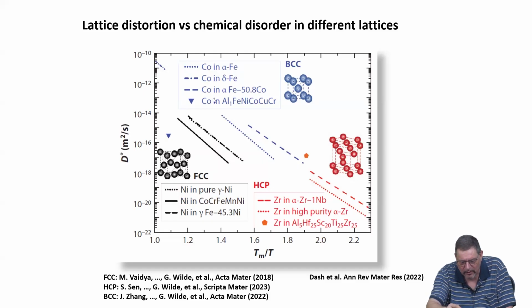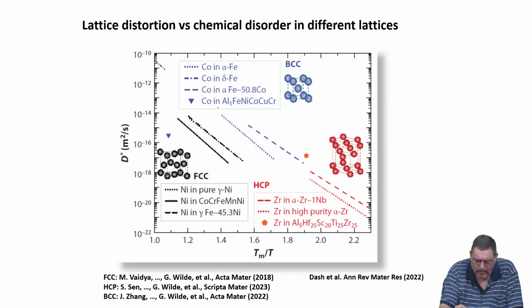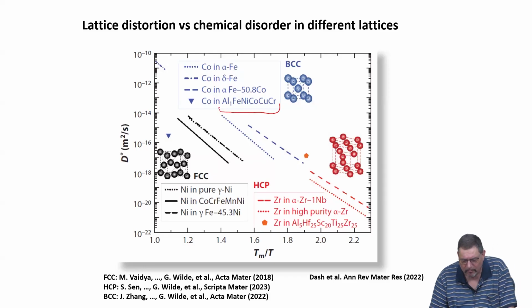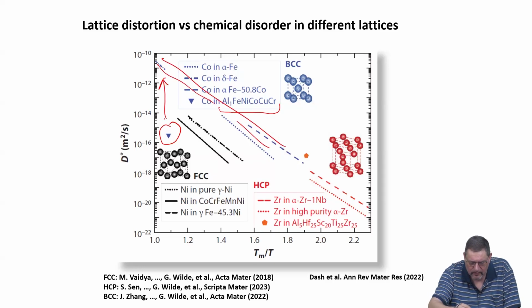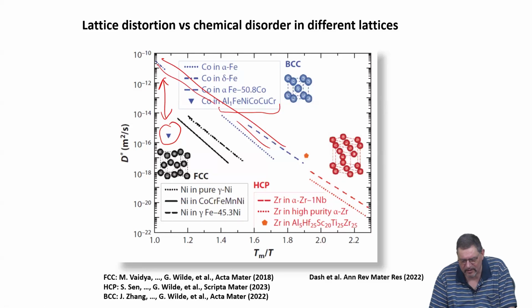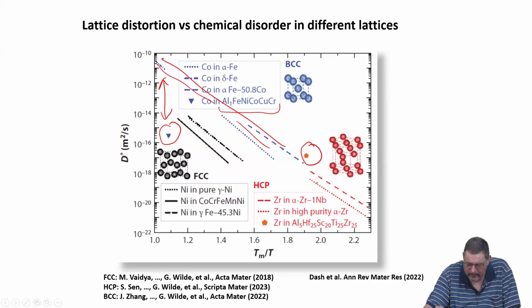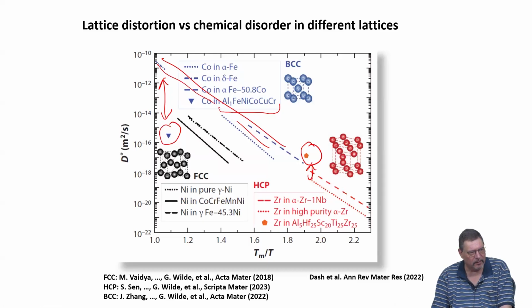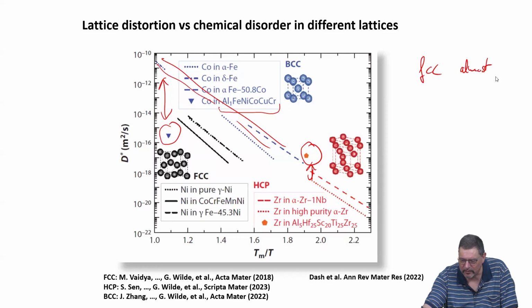So when we look here, for example, at the cobalt diffusivities, either in the pure iron phases, in a binary iron-cobalt alloy, or in this BCC variant of the former Cantor alloy, so you basically modify it by mostly aluminum, then you get a BCC phase, and then you basically see that you have here this comparison, so this value as compared to what is mostly going here. So this is certainly a deceleration of diffusion. If you go for the HCP comparison, you see that there is actually a comparison the other way around. So you have, for FCC, I would say, almost similar diffusion.